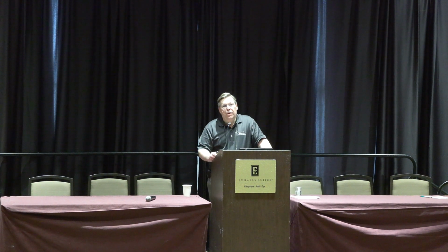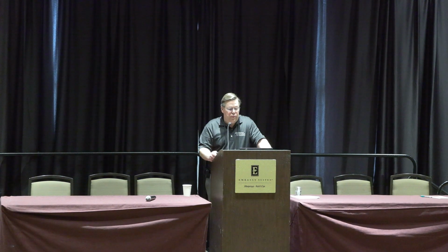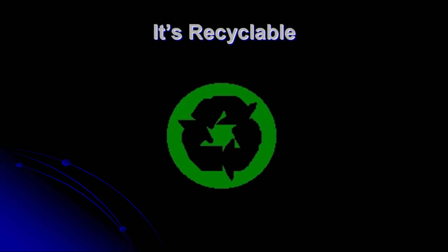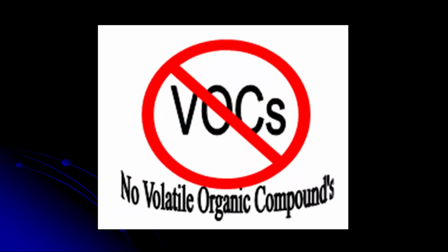If there are any impurities on the steel, the zinc will not adhere to the steel, and we call those black spots. You know it right away. You don't have to wait. This either needs to be fixed with ASTM A780, the repair of hot dip galvanizing, or if it's a really big spot, they'll just take it back, rerun the piece and re-galvanize it. They'll strip the zinc off and rerun it. Zinc is recyclable, and that's done today. No volatile organic compounds is another big thing with that.